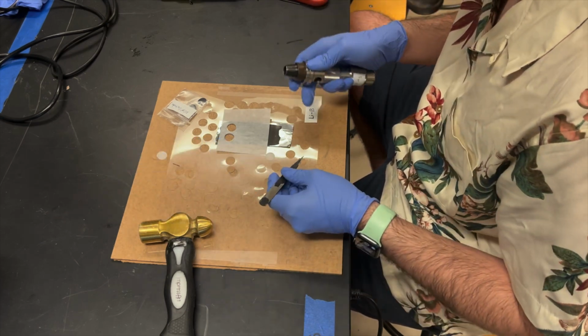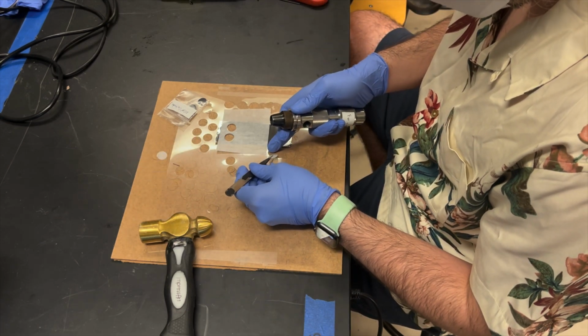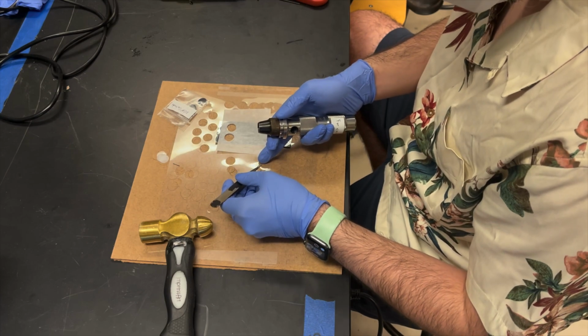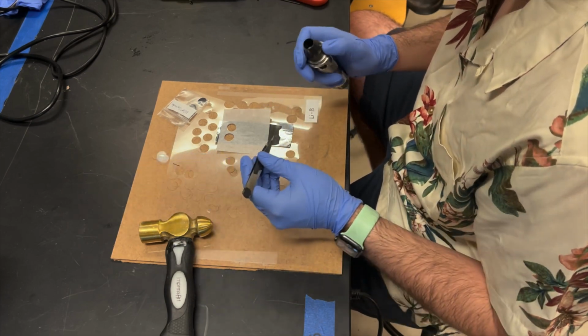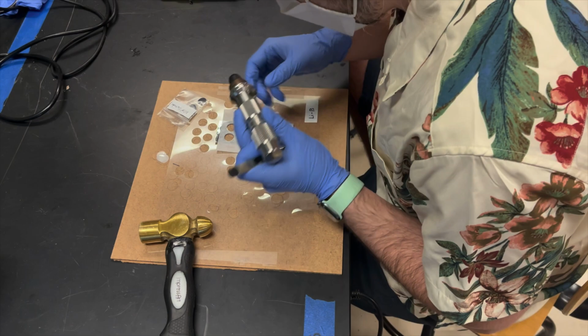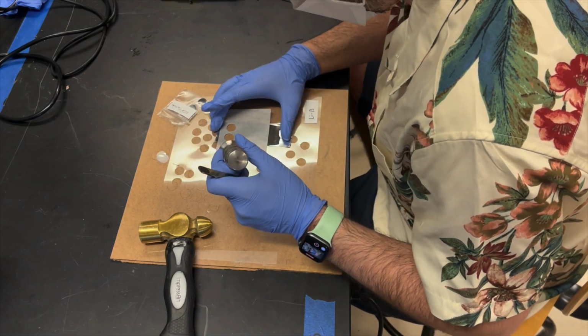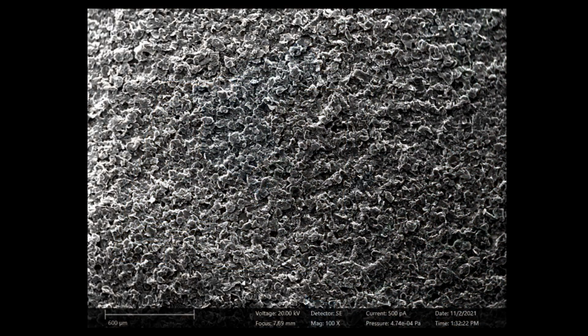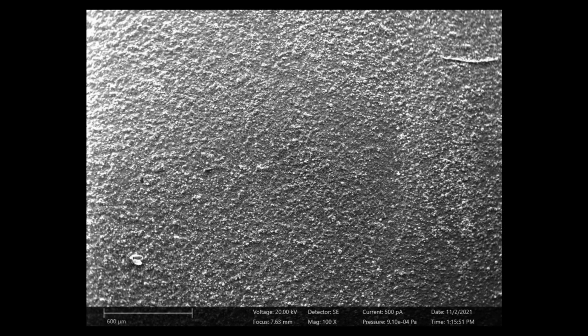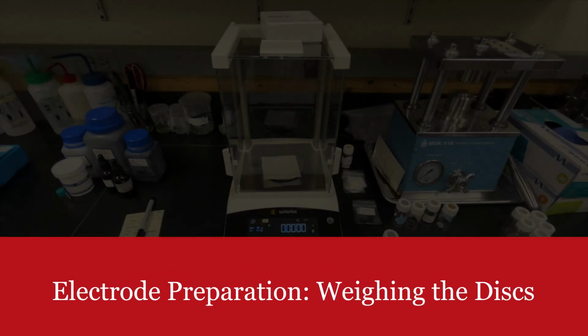A material is considered activated or active if it has a highly porous morphology on a microscale level that drastically increases its surface area available for chemical reactions to take place. On the screen then, we can see the morphology of the graphite electrode under secondary electron imaging, as well as the nickel cobalt manganese electrode, both having a highly porous surface that lends to how well they do in conducting electrons.